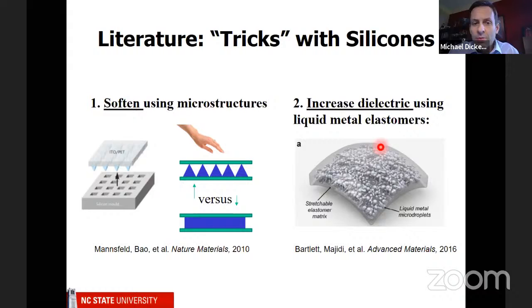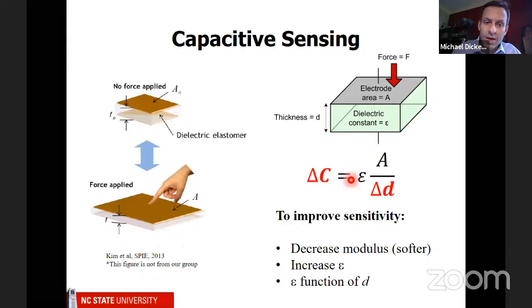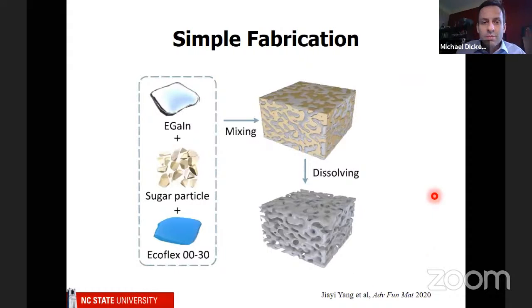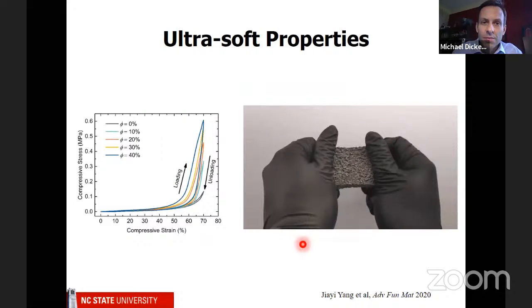Another trick that people have done is increase the dielectric by putting liquid metal into the silicone. And that increases the dielectric constant. So if I go back, it increases this dielectric. And so that helps make it more sensitive. So we did both of those things. We mixed liquid metal with sugar and silicone. It's called EcoFlex. It's just a silicone. So we mix it together and then we dissolve out the sugar and we get this porous material.